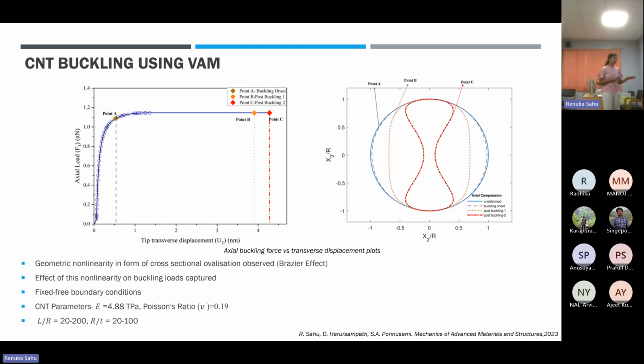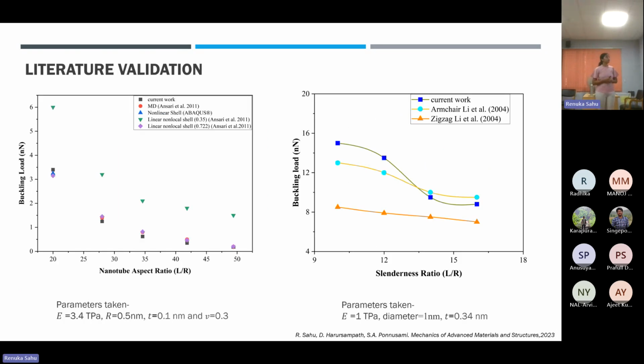For the complete study, we have taken the length-to-radius and radius-to-thickness ratios in this order, within this range. We have also done literature validation, wherein the first work we validated with was a non-local model, a non-local shell-based model.